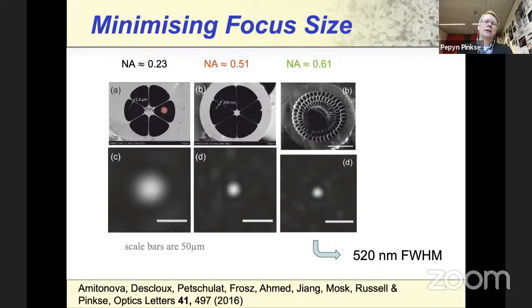And that's done in these beautiful photonic crystal fibers that were made by our collaborators at the Max Planck Institute for the Science of Light in Erlangen. Although they're called that, they don't work as a photonic crystal here, but by surrounding the core of these three fibers by a cladding of air, which makes an effective NA of 0.23 on the left, 0.51 in the center, and in the right fiber even 0.61. And if you wavefront shape your light through such a fiber, then you can actually get down to 520 nanometer full width half max in the right picture, which is smaller than the wavelength of the used light, which was helium-neon 633. So you can indeed make very small foci at the end of a multimode fiber in this way.